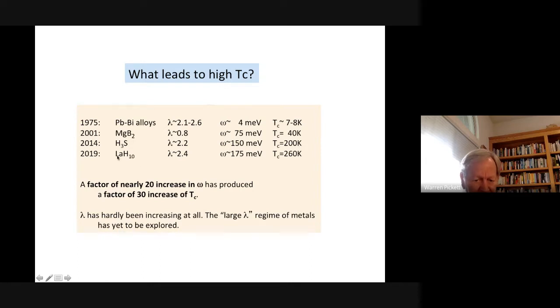And finally, lanthanum hydride, lambda calculated is around 2.4. The frequency scale is increased very noticeably here. And then the TC comes out to be a little increase here, goes from 200 to 260. And that's the highest accepted number. There's another paper out in which what was put into the diamond anvil cell was carbon, sulfur, and hydrogen. And signals of superconductivity were seen up to 280 Kelvin, which is room temperature in a cold laboratory, right?